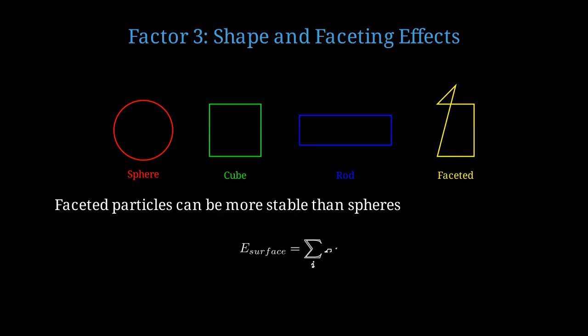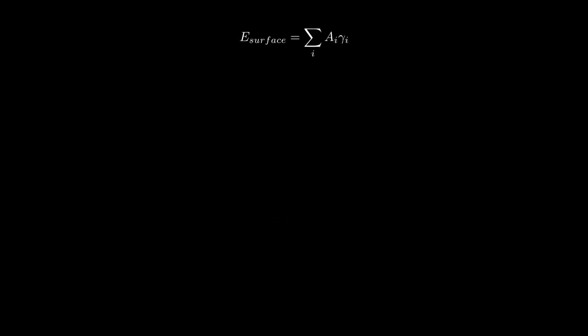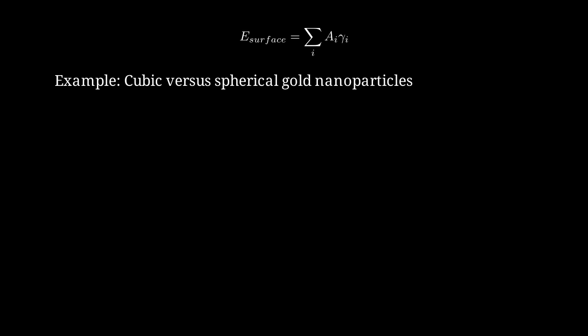The total surface energy equals the sum over all facets of area A_i times surface energy gamma_i. Minimizing this determines the equilibrium shape. Gold nanocubes exposing {100} facets can have melting points 20 to 30 Kelvin higher than spherical particles of the same volume. Now let's put it all together.